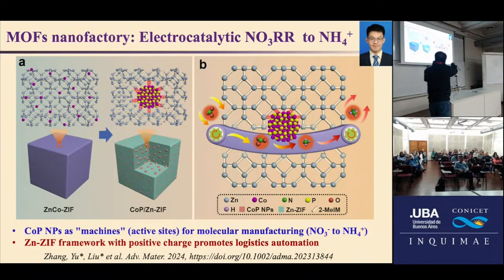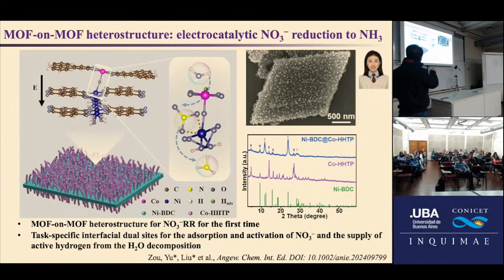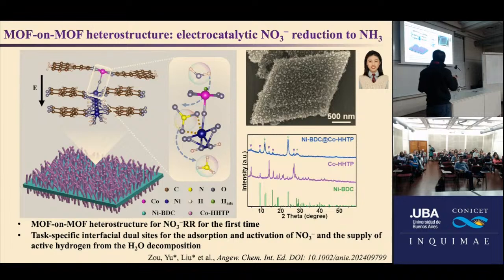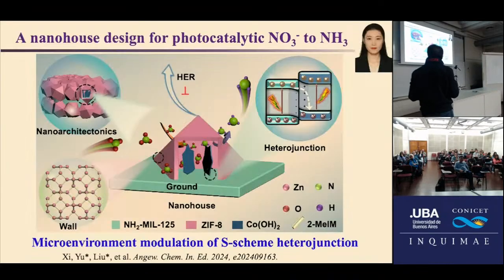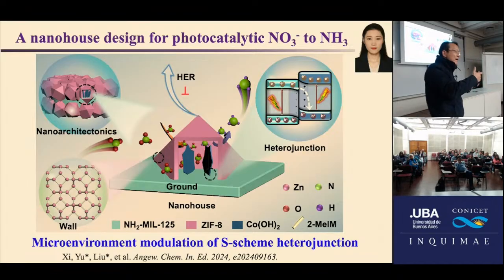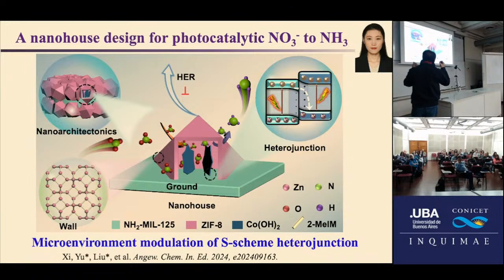And also there are multiple active sites embedded inside this framework. That's why the conversion rate of this catalyst is very high. So this is another example showing the so-called MOF-on-MOF design, also for nitrate reduction to ammonia, showing that you can form a new interface. This new interface provides active sites, and these active sites eventually give you a very high nitrate to ammonia reduction. This is not electrocatalysis but photocatalysis, showing that the nanostructure plays a very interesting role, not just looking good, but also providing very nice functionality.